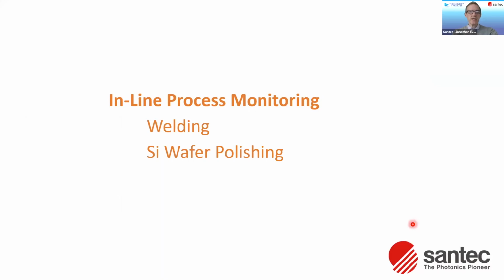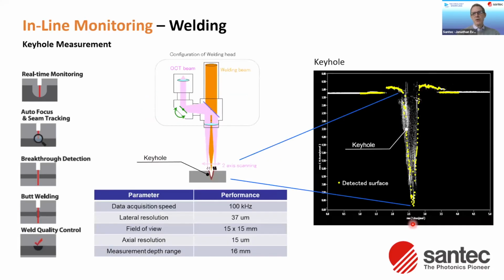The second application is inline process monitoring, and I'll talk about welding and silicon wafer polishing. In the center here is a typical setup for a high-power laser welding system. You've got a multi-kilowatt beam coming down onto the metal where the welding is taking place. At the focus of the high-profile beam, there's this ablated region called the keyhole, and to assess the quality of the weld, it's important to have real-time monitoring of the geometry of the keyhole.